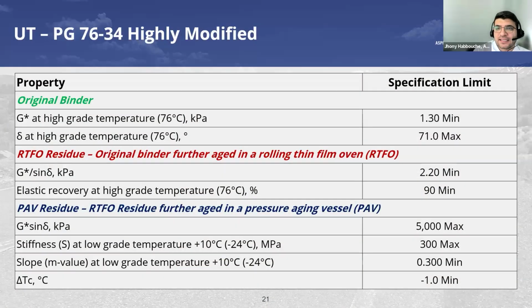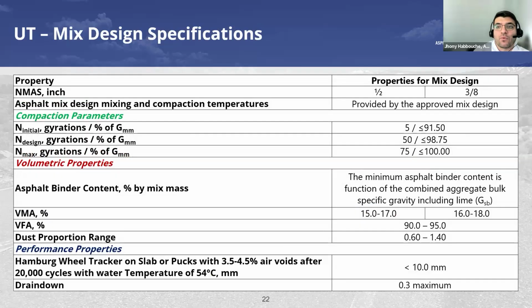Just to remind you, this is the specification for the binder in Utah. Again, I'm repeating myself here. That percent recovery, then everything else remains the same as a typical PG grading following the AASHTO M320. But as I mentioned, they do have a requirement on their mix specification. They do their N design. You see, they're designing their pavement mixtures down to about 1% air void.